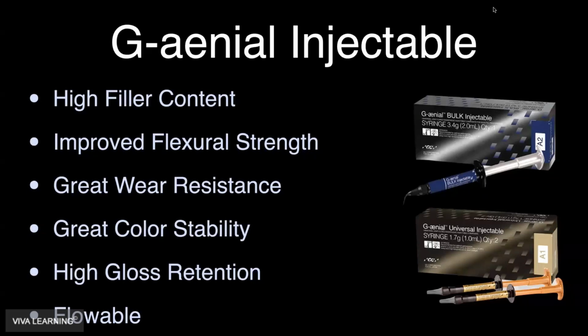And what they did was they actually take those filler particles and they coat those filler particles so that it reduces surface tension. We're all kind of familiar with that. That's exactly why we put silane on the inside of a ceramic restoration before we bond it in to reduce the surface tension, or you might be using like an MDP product on the inside of your ceramics. All of that is designed to reduce surface tension. And when you basically coat all of the filler particles prior to putting them in the organic matrix with a chemistry that reduces surface tension, not only do you have smaller particles, so you can put the same percentage as a denser material and it maintains a lower viscosity, but those particles can now slide past each other more easily, and therefore you don't get that increase in viscosity.